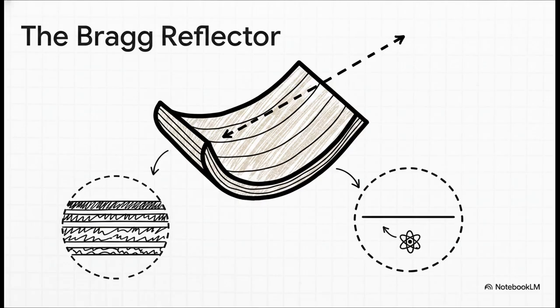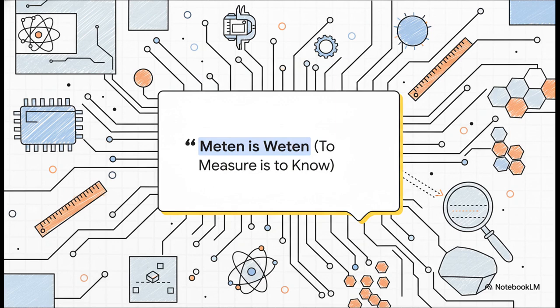Each one is built from dozens of alternating layers of silicon and molybdenum, and each layer is only a few atoms thick. They're designed so that when the EUV light hits them, the layers work together to reflect about 70% of it. And the surface of these mirrors? They are so flawlessly smooth that across the whole surface, the imperfections are smaller than the width of a single atom. It's just perfect.